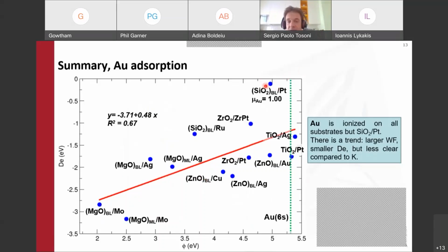As you can see, there's a remarkable outlier here, a silica bilayer on platinum. Even though we could expect the charge transfer to take place because the acceptor state is higher in energy compared to the 6s orbital of gold, the charge transfer does not actually take place. We still have spin density on the gold atom that maintains the electron configuration as an isolated atom. As you can see, in general, the trend is worse compared to the case of potassium.